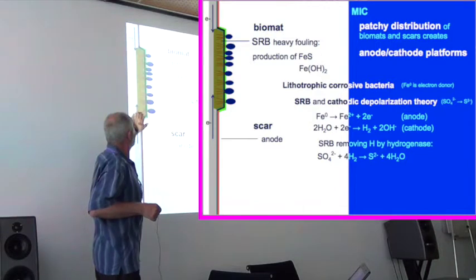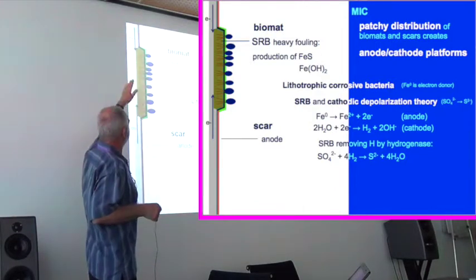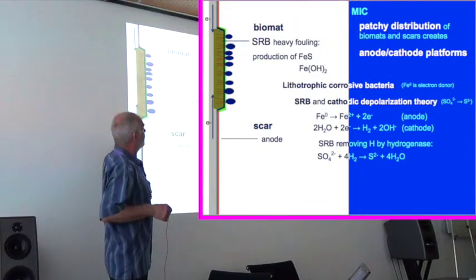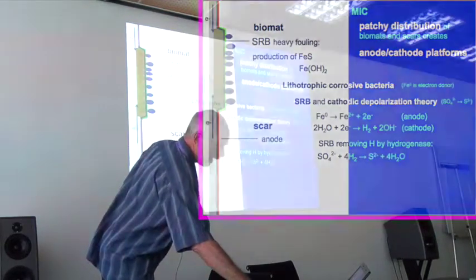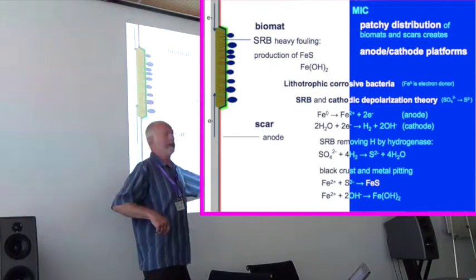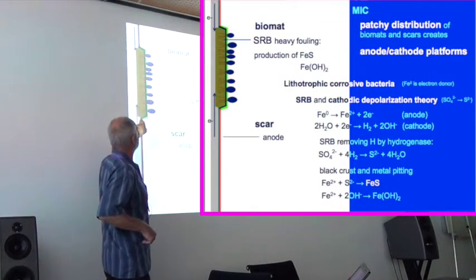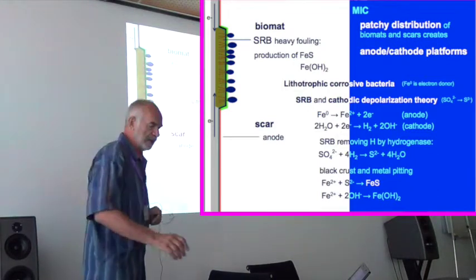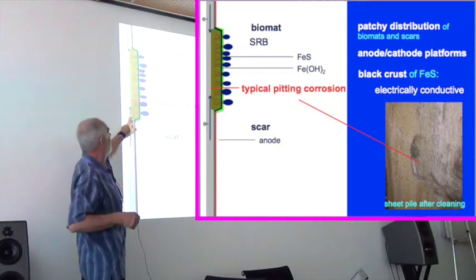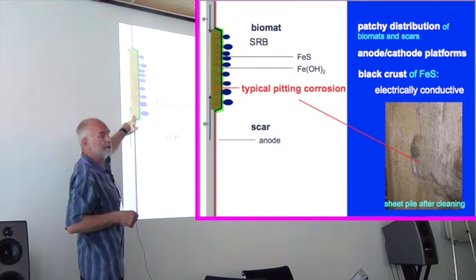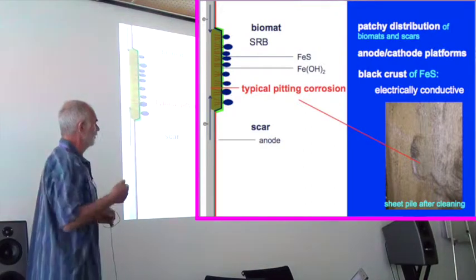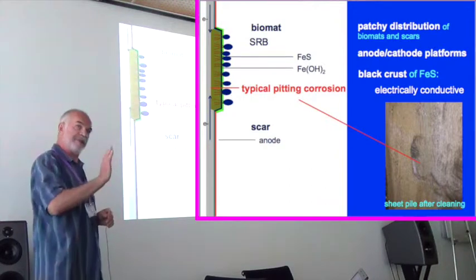It gives a very strange type of pitting. Here on your substrate, in such a platform, an anaerobic cathode platform, they are flourishing sulfate-reducing bacteria, so lithotrophic. And moreover, as a result of chemical reactions, you have the production of iron sulfide, here represented by that black line. Important here is the first demonstration of the consumption of iron by the sulfate-reducing bacteria community. And it's very nice seeing, on your sheet pile, after handling, that these flakes are imprinted on the substrate.